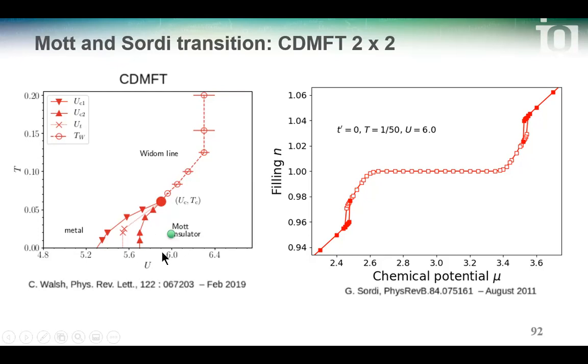You don't expect that the expectation value of n up n down has anything to do with an order parameter, but here it actually does. So it's like a liquid-gas transition in some sense. It has a scalar order parameter, and this critical point is in the Ising universality class. In the case of the Sordi transition, it's the density that jumps from here to there, so you can take the density as the order parameter, in the same way as in a liquid-gas transition. It's again in the Ising universality class: it has a first order transition, a critical point, and the exponents are those.